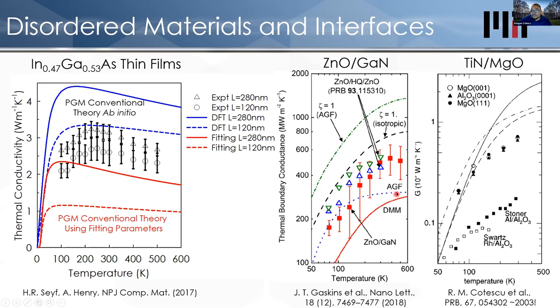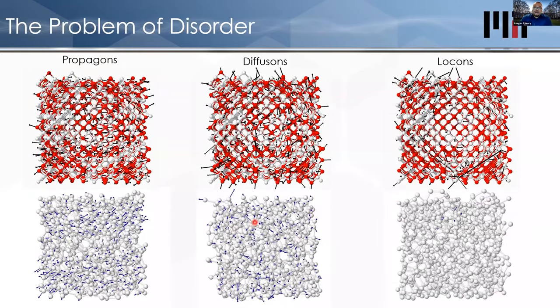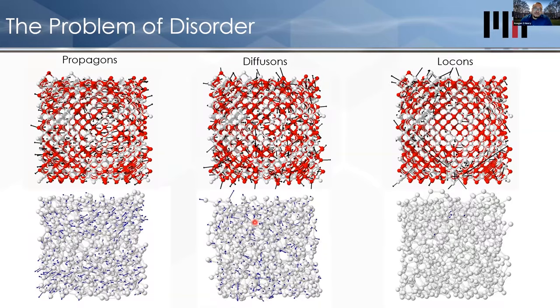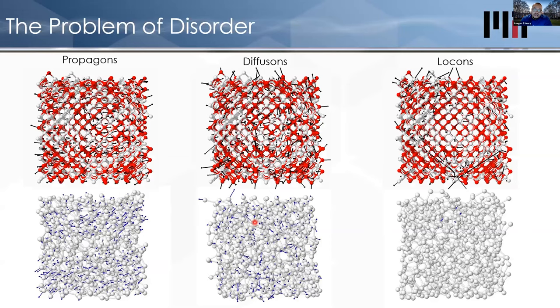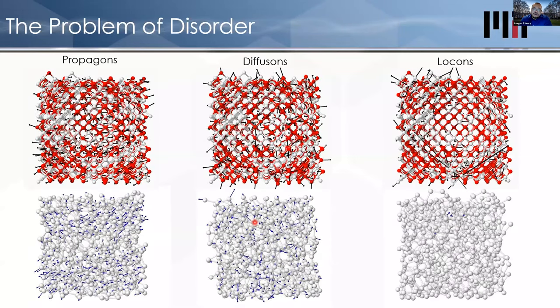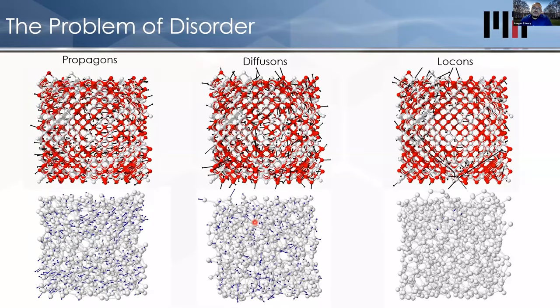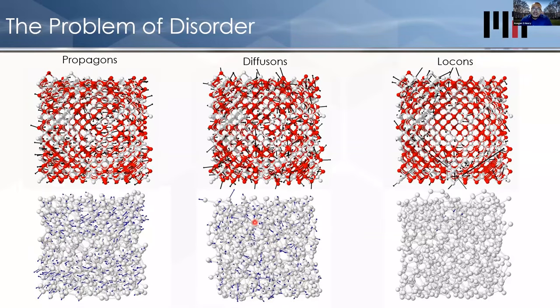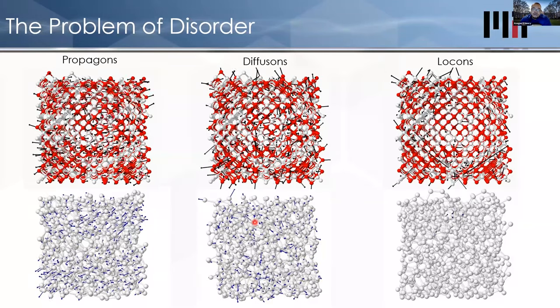Similar things happen if you have disorder in the form of breaking symmetry by having, like, an interface between two different materials. If we try to describe the interface resistance or interface conductance between different materials, again, here's theory, you see lines all over the place, and then the data is not matched by the theory. All right, and so we again see big discrepancies between theory and experiment when we have systems that are disordered. In short, I'll just jump to the punchline. What we found is wrong with this model is that when you break symmetry, the phonons no longer look like plane waves anymore. And that's the core problem. And once they don't look like plane waves, then the whole particle analogy breaks down and everything becomes problematic.